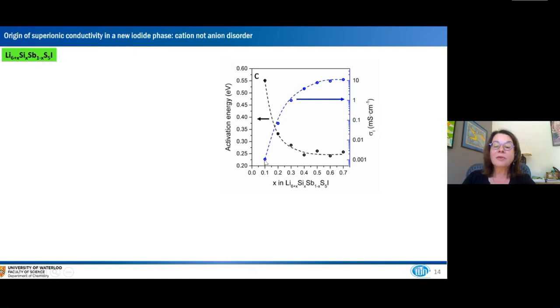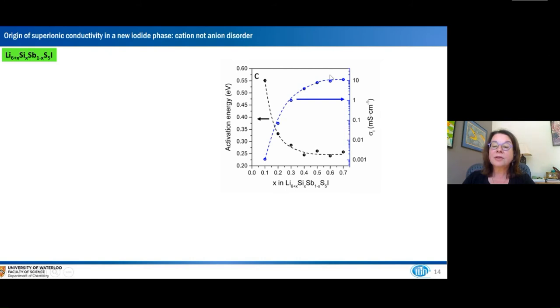So we've taken the conductivity from very low values, shown here, all the way up to 10 millisiemens, and in fact above. You can see in this plot that as the conductivity increases, the activation energy drops as expected. And this increases with silicon substitution, and the silicon substitution for the antimony also increases the lithium content.